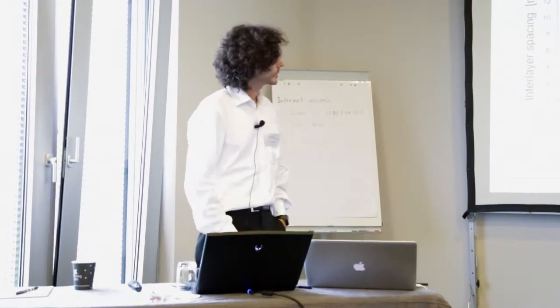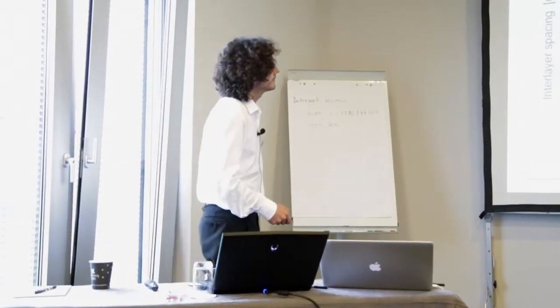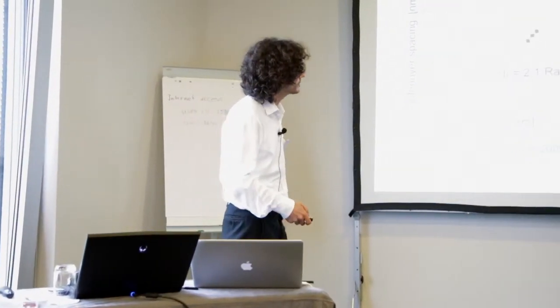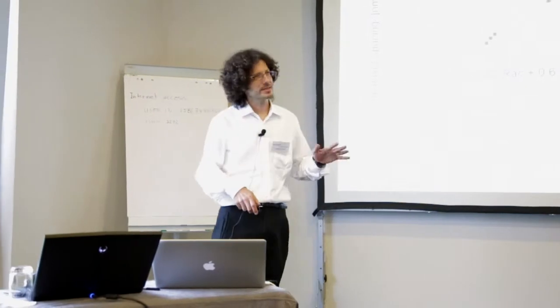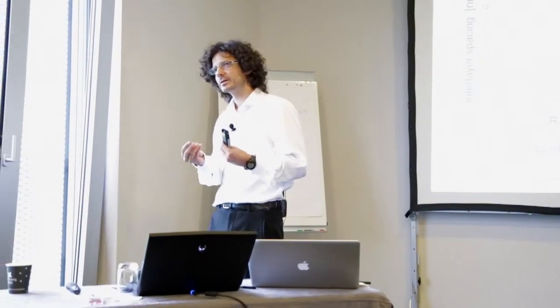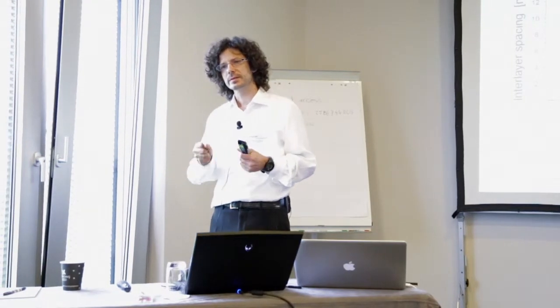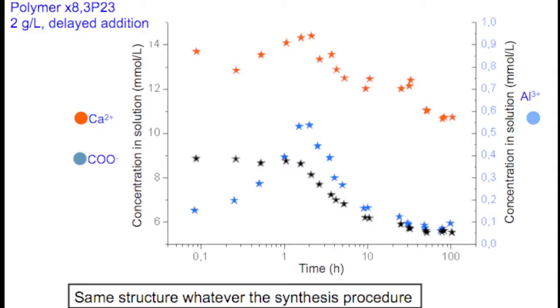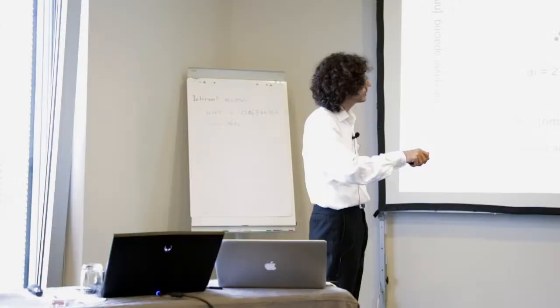And the nice thing also was that, this is where I was particularly happy, but whatever, we had in a separate study by atomic force microscopy concluded that the adsorbed polymers had to have coiled side chains and that there would be a scaling law approach that we could use to infer the characteristic dimensions of the polymer and a characteristic dimension if two layers with adsorbed polymers would come into contact before you would have massive steric repulsion.